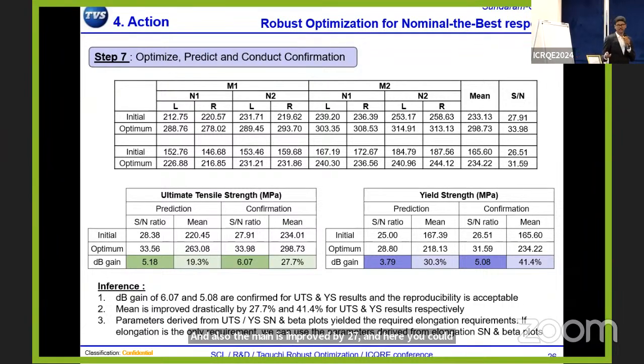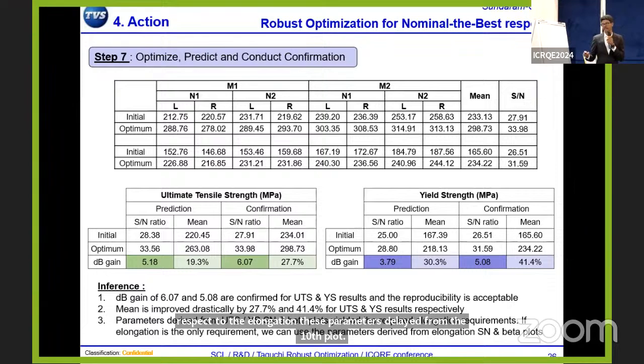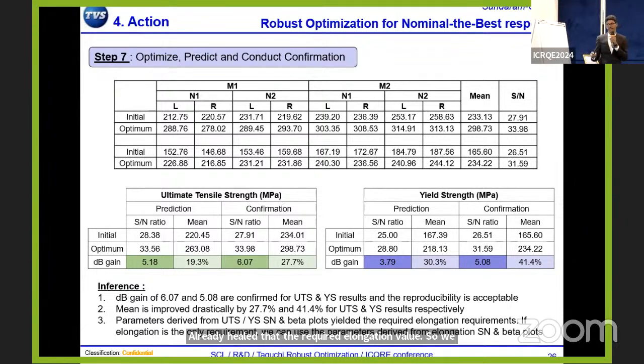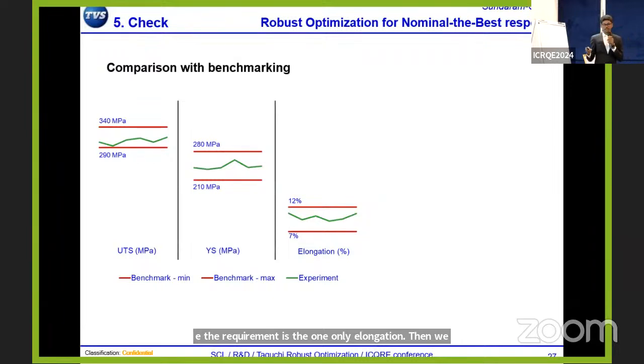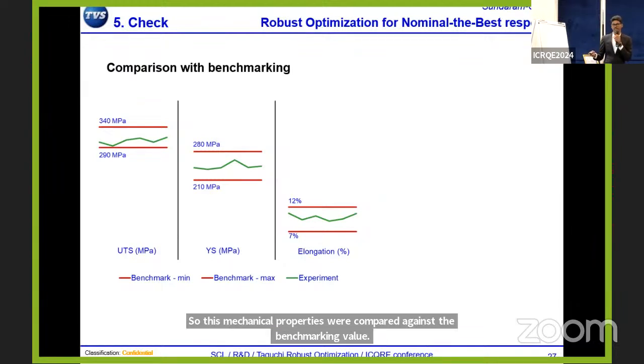With respect to elongation, these parameters derived from the strength plot already yielded the required elongation values. So we didn't use the elongation optimal parameters. Suppose the requirement is only elongation, then we can go for that second level of parameters. Okay, so these mechanical properties were compared against the benchmarking value. You could see the values are within the benchmarked limits.